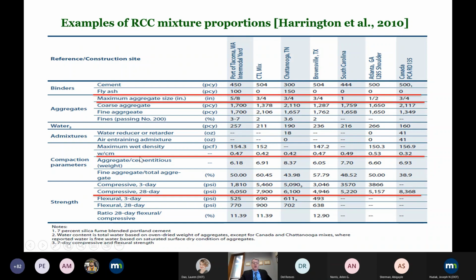And then in terms of water to cementitious materials, you see the Canadians, where they air entrained the concrete, lower the water to binder ratio down to 0.32. But here in the US, 0.42, 0.47, up to 0.53 seems to be consistent. And for compressive strengths at 28 days, you can get between 5,200 PSI and about 8,000 PSI, and flexural strengths also between 640 and about 900 PSI. Now, this is important because later on we'll come back and look at the densities and the flexural strengths and compressive strengths, which of course are very much affected by the density and the compaction energy of the pavement.